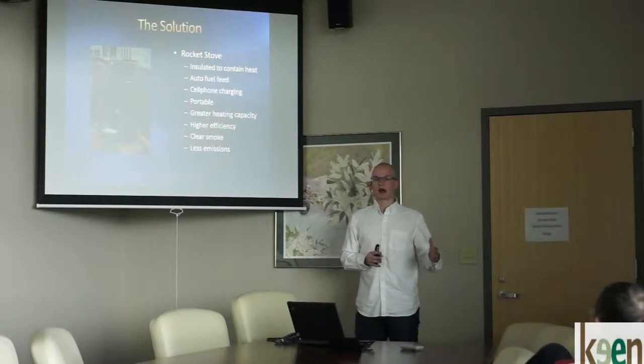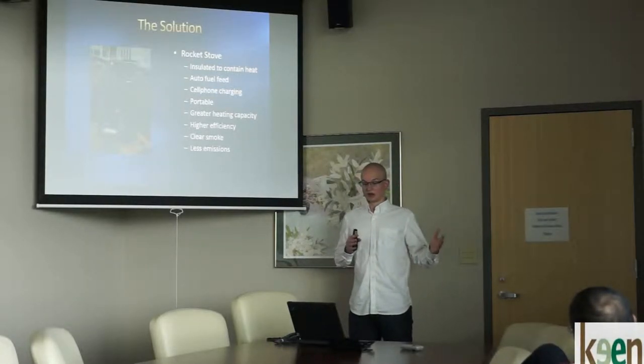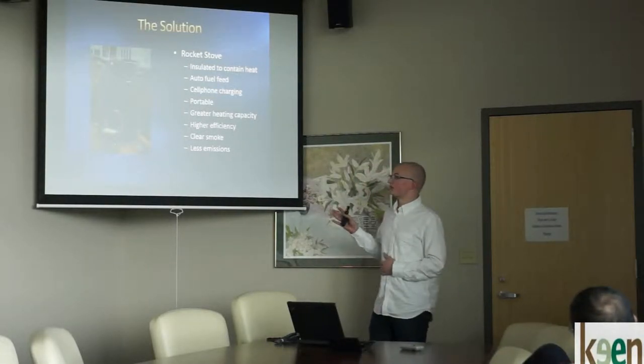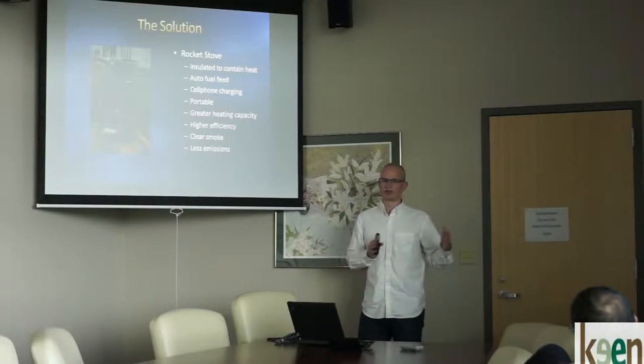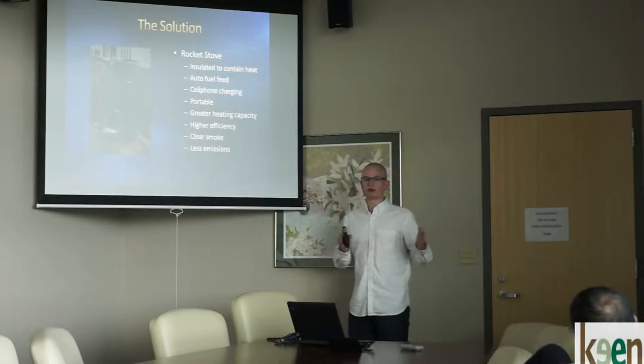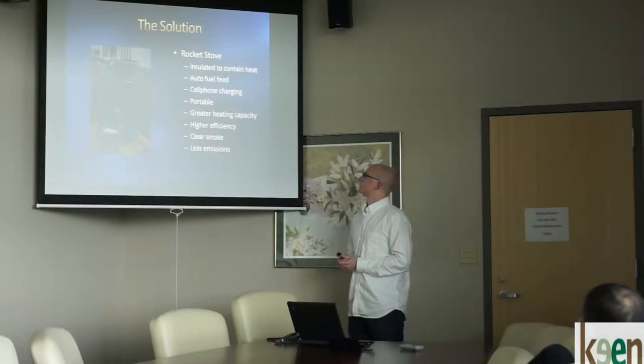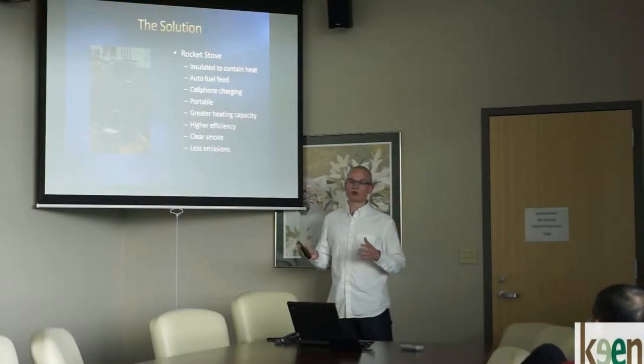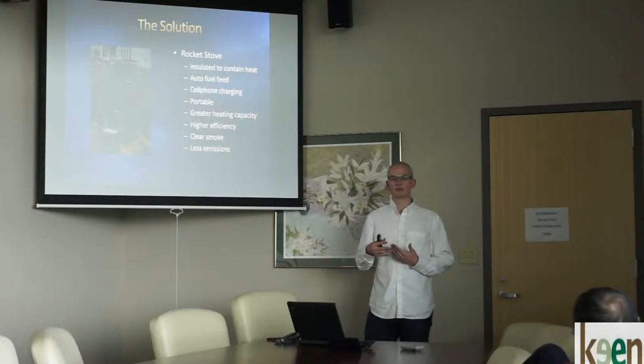We made a lot of strides to decrease its weight because even earlier prototypes of this stove were considerably heavier, in the range of 30 to 40 pounds. That was mainly due to the insulation. It also has greater heating capacity: for the same amount of fuel, this stove put out about twice as much heat.